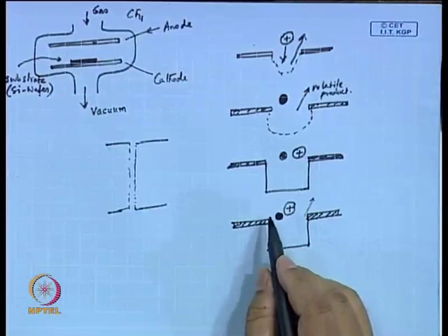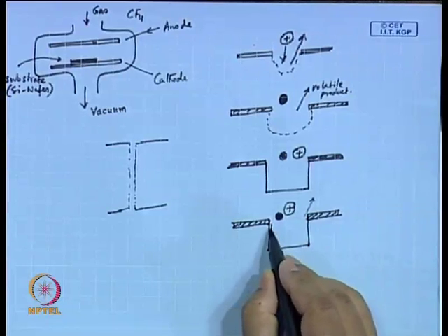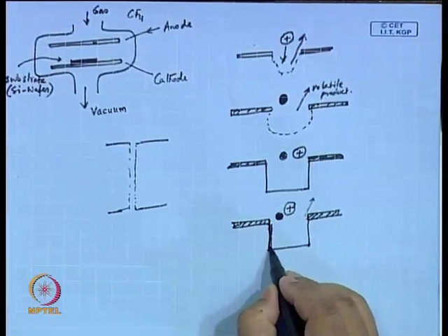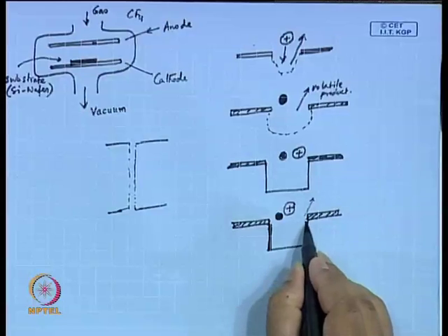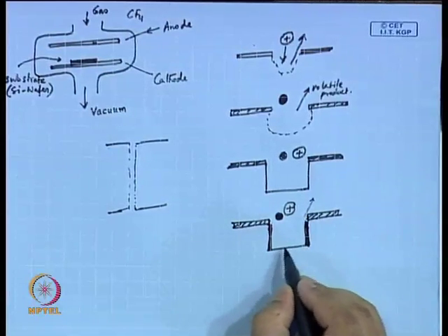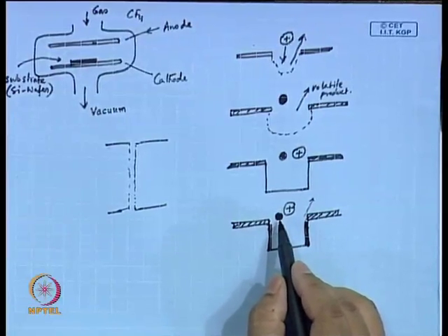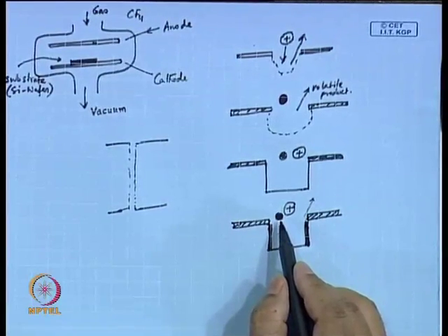What you end up with is a coating forming. This inhibitor will form a coating, this is the layer, on the vertical wall. This coating is made of the product of this chemical etching process.